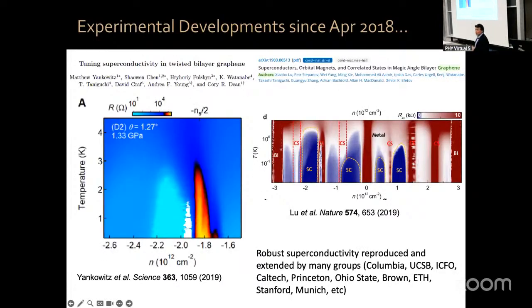The first two groups to reproduce our results were these. The first was a collaboration between the group of Corey Dean at Columbia University and Andrea Young at the University of California, Santa Barbara. They did a very nice experiment. First, they made a sample at the magic angle, 1.1 degrees, and saw correlated insulators and superconductivity, the exact same thing we saw. Then they made another device at a larger angle, 1.27 degrees, and when they measured it, they did not see correlated insulators and superconductivity.